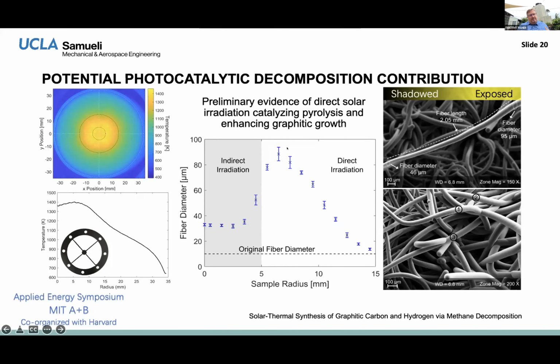Now, you might say, well, maybe that's because the directly irradiated part became a lot hotter. But it turns out, since we're growing basically graphite, the thermal conductivity, and we have some measurements of that, is very high, and we do not expect there to be a large temperature gradient across a fiber like this. In fact, it's almost negligible, which means that the temperature of the fiber in here is the same as here, yet the deposition rate is much higher in a directly irradiated part. I hope to have much more to say about this, because we're studying it very carefully. But there is some kind of significant direct photolysis effect happening in this process. I am convinced of that.